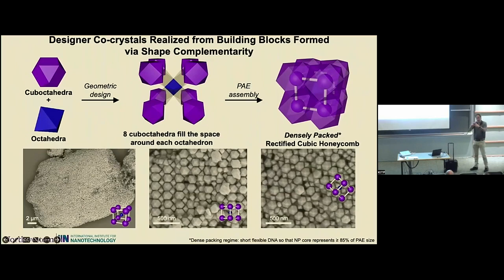And the trick here is to actually use short oligonucleotides. We actually had to design new ones, but that have, and this gets to your talk, a little shock absorber on them. Because to me, it's really remarkable that this works at all, right? Because one is you have to have the perfect match in terms of the shapes, right? And the sizes, the dimensions of the two particles. And it's impossible to do. You just can't do that from a synthetic standpoint.